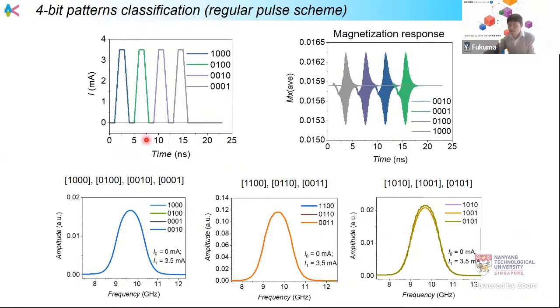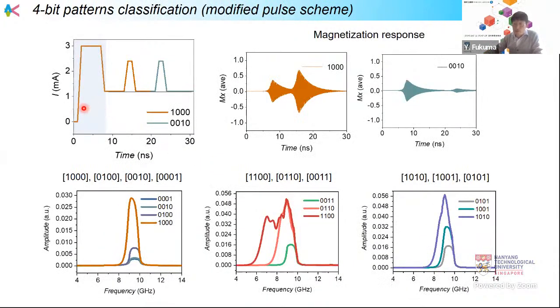That's why this kind of scheme does not work for the classification task for the 4-bit pattern. That's why we use this kind of fast excitation pulse, then turn on the continuous current here. Then we put 1 0 0, for example. This is the case of 0 0 1 0. In this case, the first excitation part is within 10 nanoseconds. Then here is just this excitation part. Then after that there is the computation task.